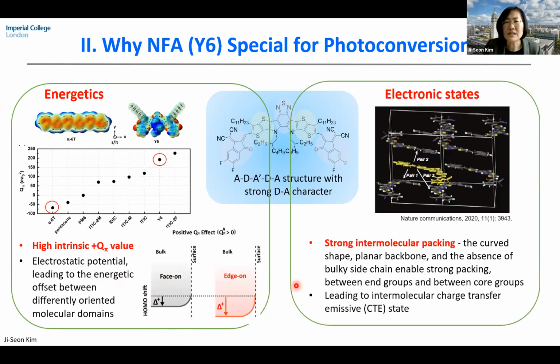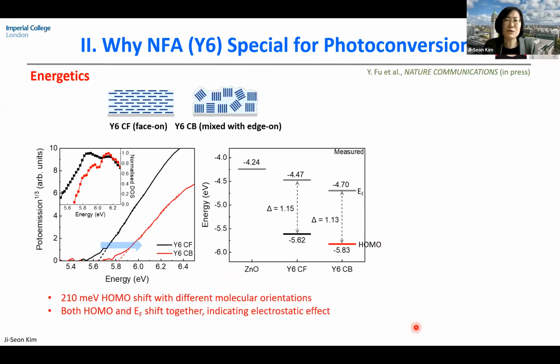Y6 is also very well known for having very strong intermolecular interaction. So when you consider a solid state thin film, there will be a very strong interaction between end-to-end groups or core-to-core groups of Y6 molecules, which will actually form an intermolecular charge transfer, particularly emissive state. So we were trying to manipulate the energetics and then the electronic state, particularly using different solvents. Using chloroform or chlorobenzene, we were able to control either a more face-on or more edge-on kind of structure. And when you measure energetics, you can clearly see almost 210 meV HOMO shift of the Y6 molecule. And when you measure the Fermi energy level shift together with the HOMO energy level, that is one of the important characteristics of an electrostatic potential effect, not a dipole-induced vacuum level shift.